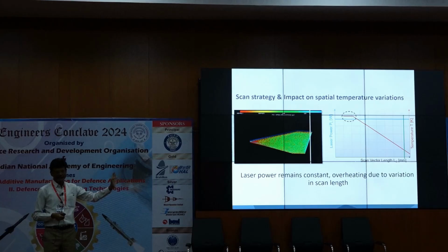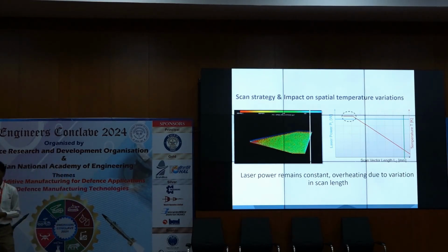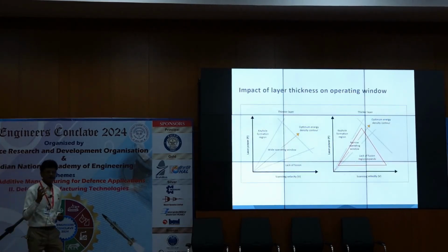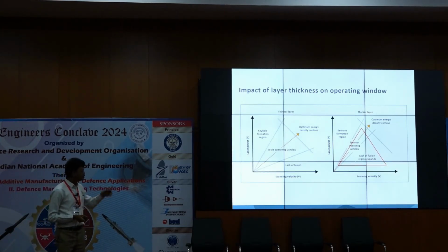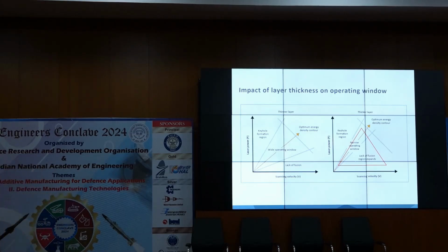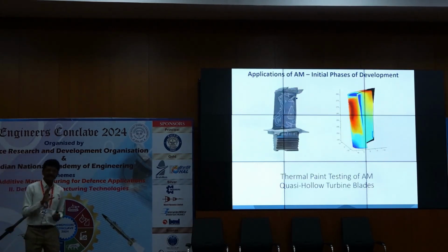Imagine that you maintain the laser power constant and you are scanning across. Despite the fact that you maintain the laser power constant, just because there is a radical change in the cross section, suddenly there is a peaking of temperature which may lead to the spatter in much excessive manner, leading to the residual porosity. So what do you do in this case, and what are the basic possibilities in terms of doing the experimentation and getting information into the behavior? So we start looking at different parameters like the layer thickness, hatch spacing, peak temperature. Then we are also looking at the specific heat of fusion, etc. and trying to develop these process maps which take into cognizance all the possible variations in the materials and their processability.